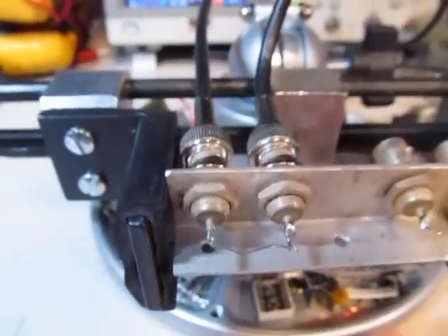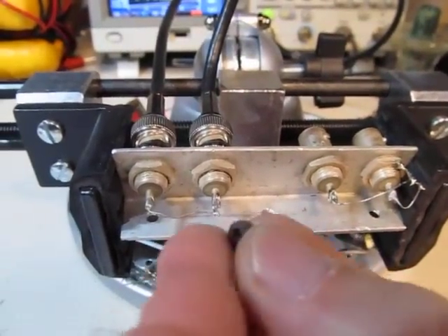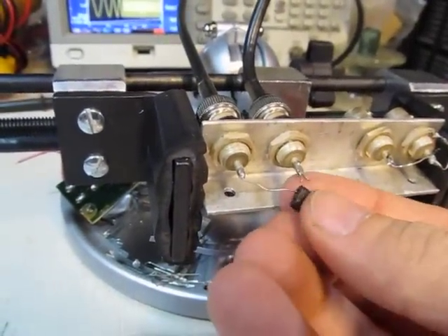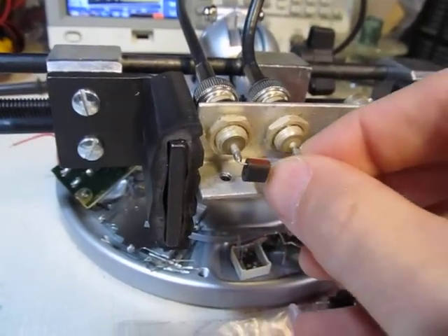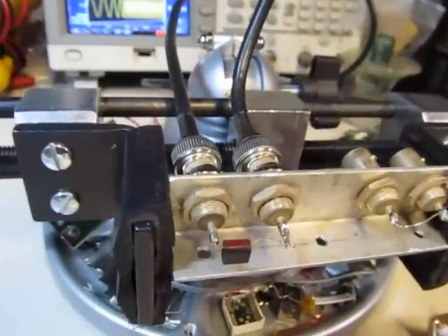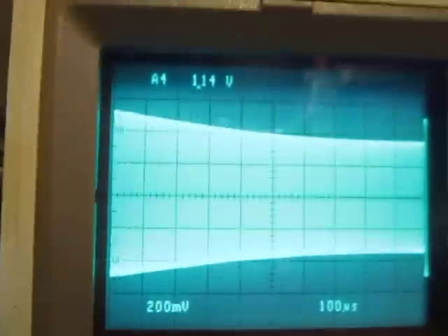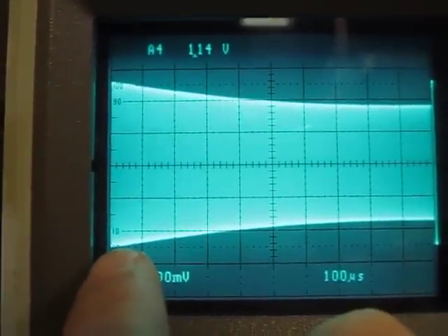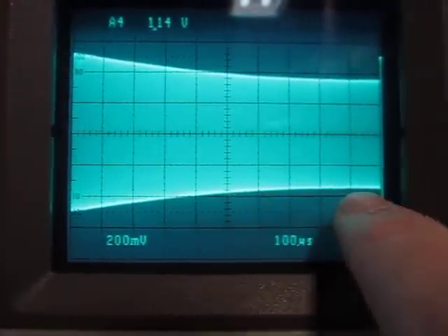If we put some frequency-dependent device in series here, we'll see that effect on the scope. I'll grab one of these ferrites — this one has two holes but I'm only going to use one. I'll pull this wire off, slip the ferrite on there, and jam it back in place. Now that ferrite is just on the wire. Looking at the scope, you can see that 10 kilohertz is really not affected, but out to about 20 megahertz I've lost some amplitude — just by slipping the ferrite on the wire, I've introduced some loss.